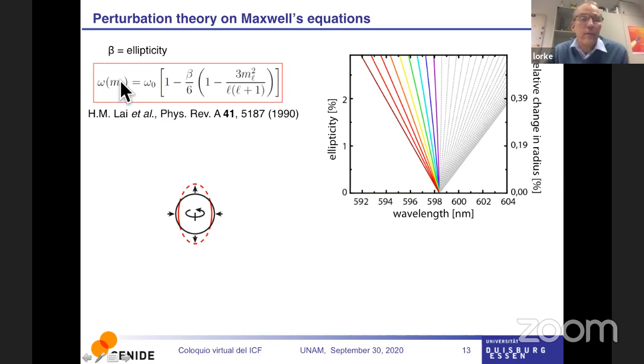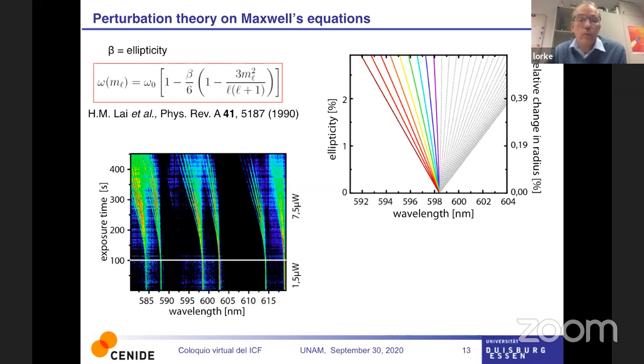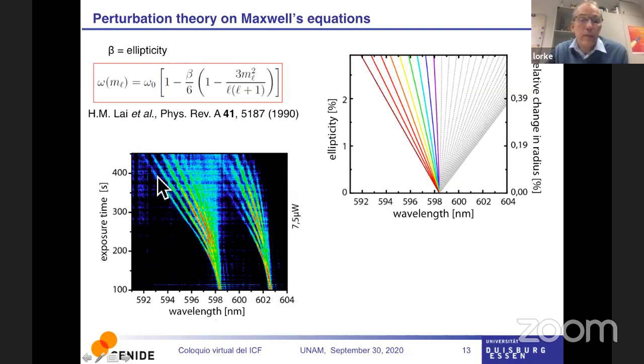And then you get that the resonance frequency, which used to be omega 0, a fixed frequency, starts to fan out according to this term here. This is only the first term in a very long series, where the ellipticity goes in and the L goes in and the m_L. And Daniel took this formula and looked at how much we can find out about our splitting here. And this is the picture that I had shown you before. Let's look at this part of the picture in a little bit more detail. And you can see how it fans out.